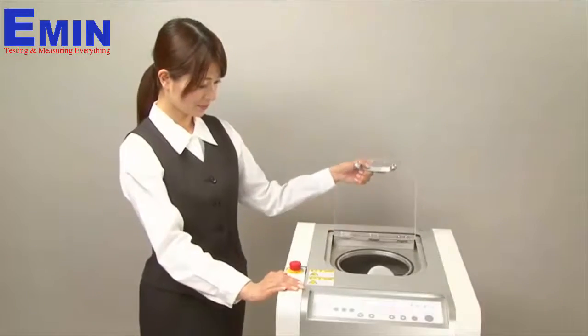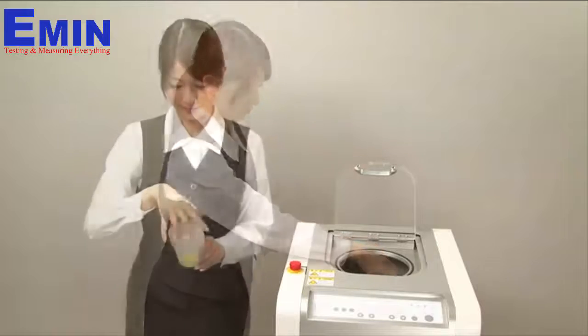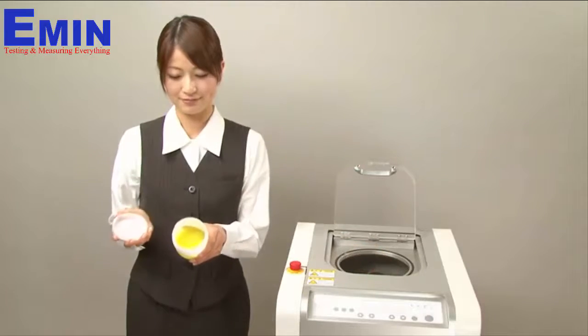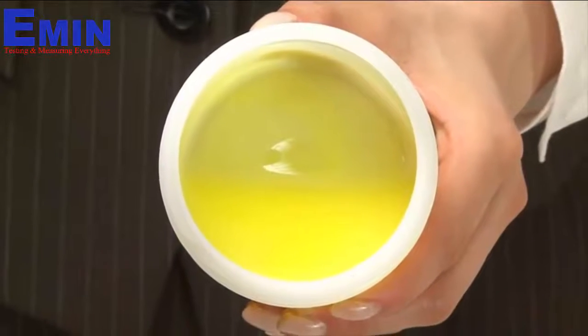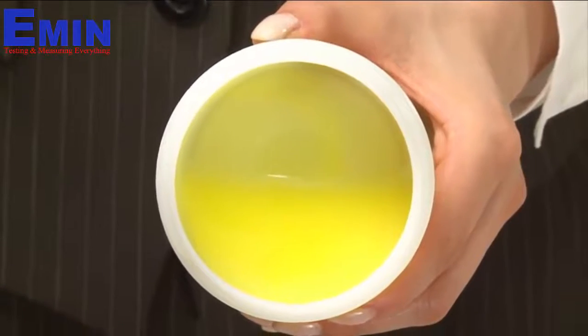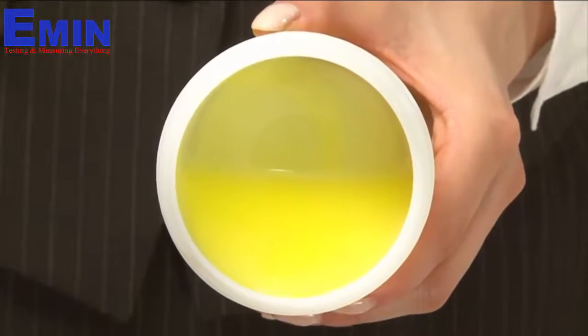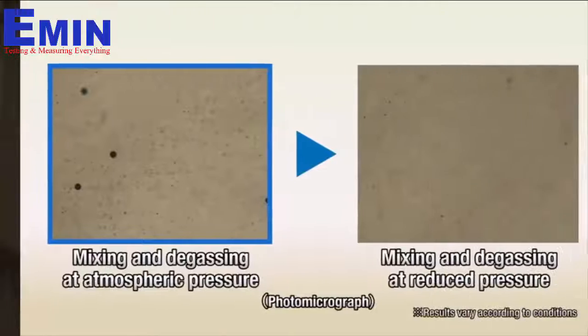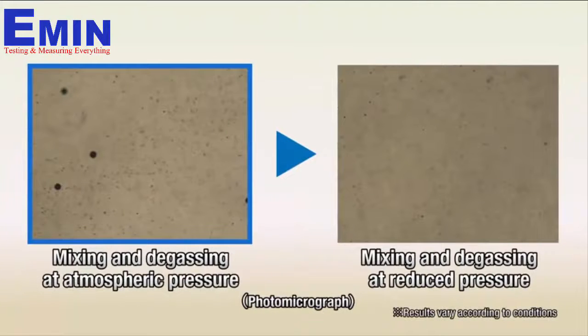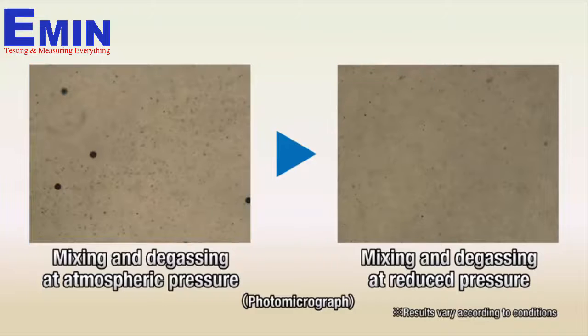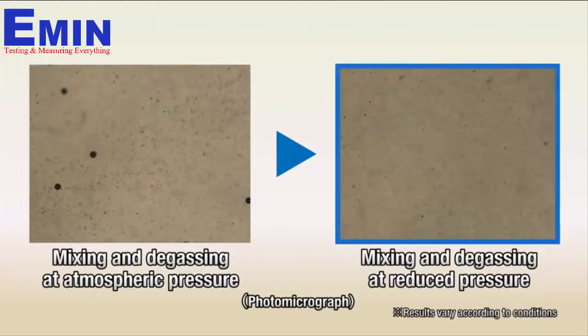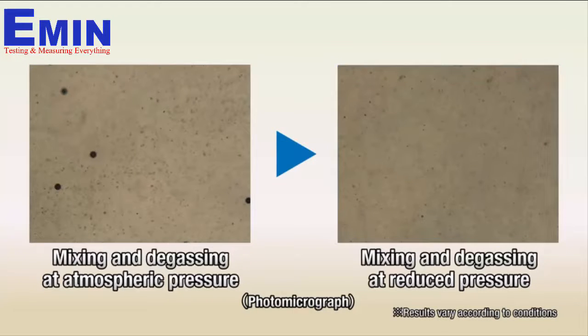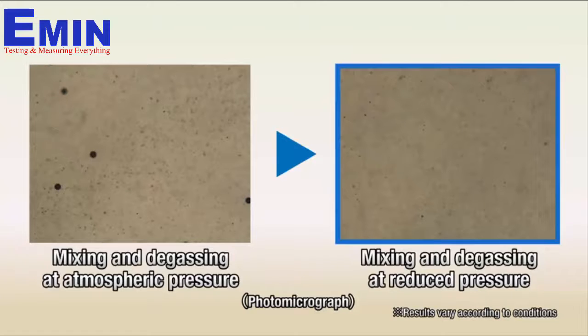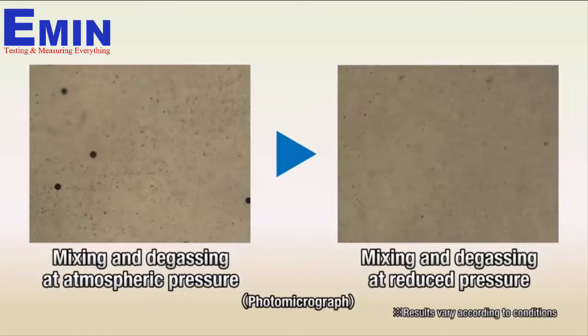See for yourself. Using two-step processing and a depressurized environment, materials of differing specific gravities have been completely mixed and degassed. In the photo on the left, trapped air has been broken down into an infinite number of microscopic bubbles through vacuum decompression. Even the microscopic bubbles are removed, as shown by the photo on the right.